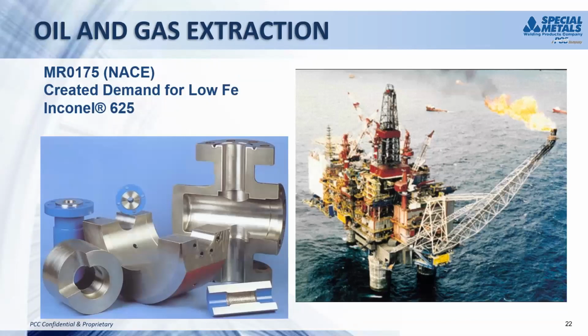Another very commonplace, popular area for Inconel 625 was in the oil and gas extraction industry. A lot of the different low alloy component pipes and valves were clad with 625 to really protect and extend the life of those valves, where if you made the whole thing out of steel, you'd start seeing some pitting and some corrosion very quickly around some of those seal components, which would cause them to fail very fast.